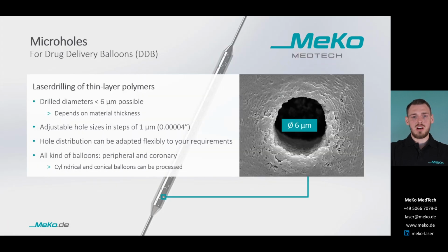Besides laser cutting of stents, there are many more use cases for USP lasers. One of those is laser drilling of thin layer polymers, which among other applications is used to drill micro holes in balloon catheters. Those drug delivery balloons can, for example, be used for the treatment of stenosis, and the picture on the right shows an SEM photo of a single hole with a diameter of about 6 microns. The drilled diameter is adjustable in steps of 1 micron, while the hole distribution can be adapted to the requirements. And of course, as in most cases, cylindric balloons are more favorable for processing, but it is also possible to process conical balloons.